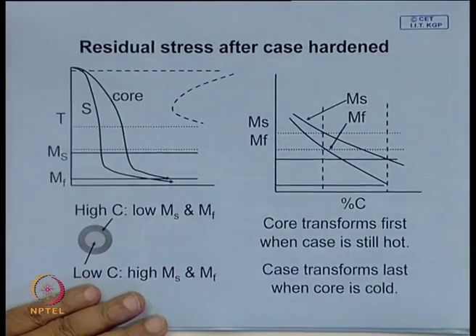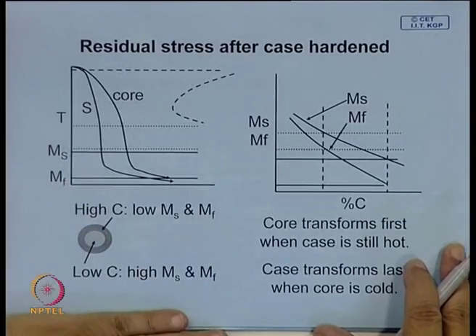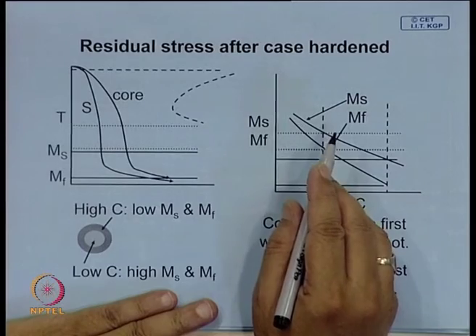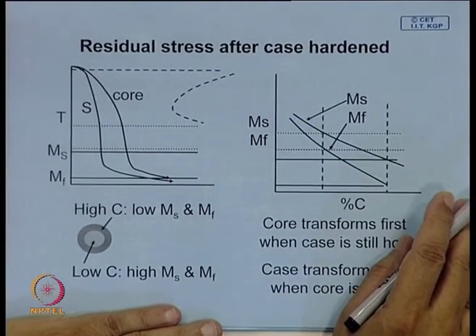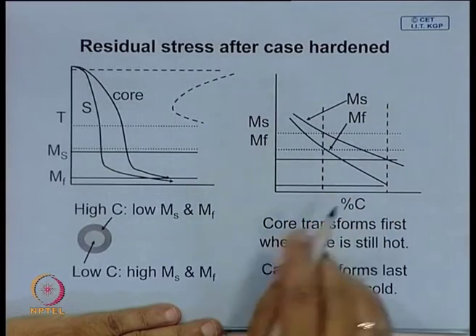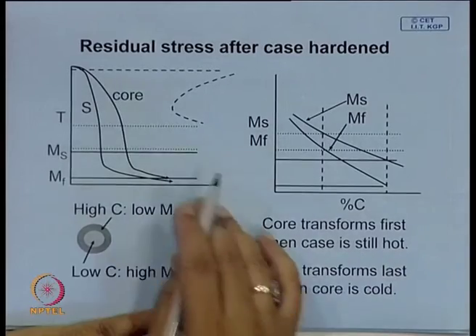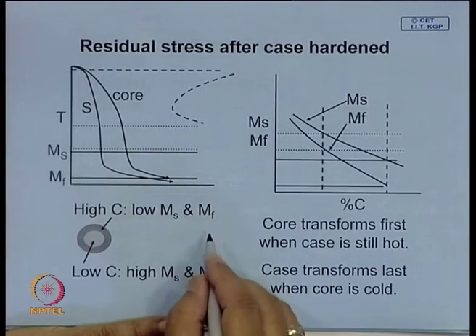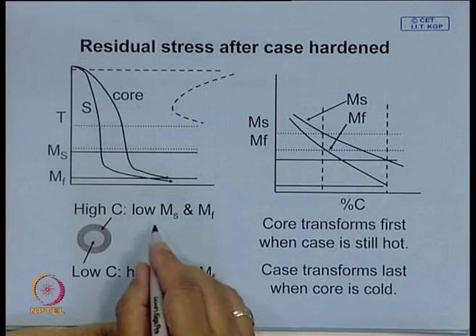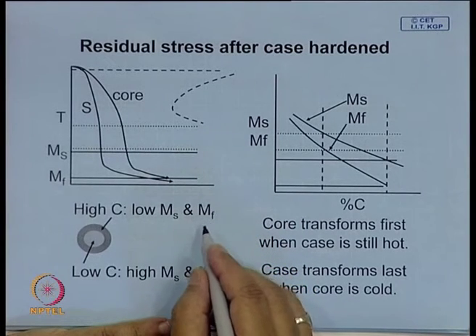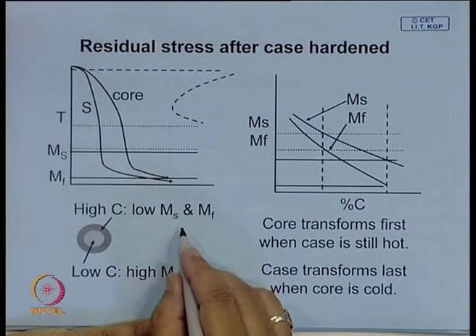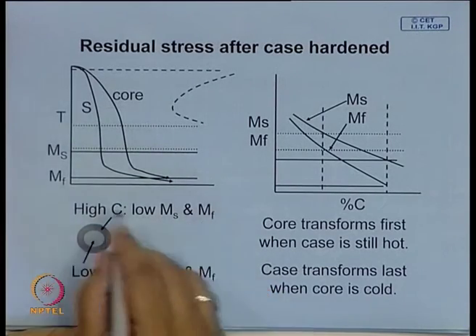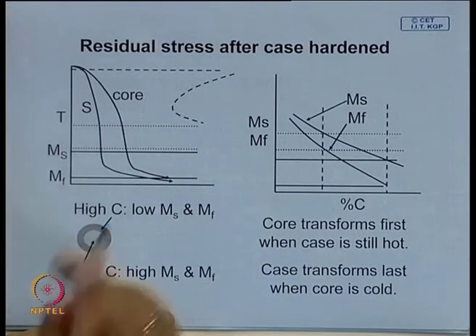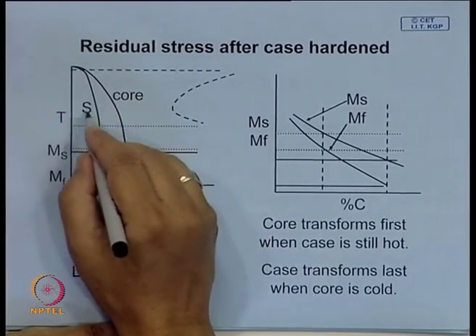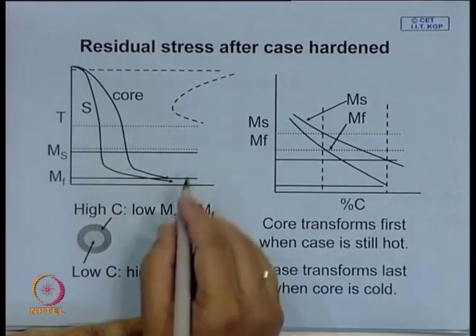And last class we talked about the limitations of hardening a steel, because this is totally dependent on the section size, and in many cases if the section size is large, it cannot be hardened. We have seen that by quenching the strength of steel can be increased many folds. So this obviously is the most obvious choice for strengthening, but it cannot be applied because a full martensitic structure can be attained only over a very limited thickness, depending on the type of steel that we use. This has been used very effectively in cases where the composition is modified, and we talked about case hardening.